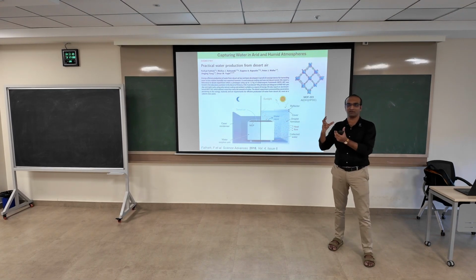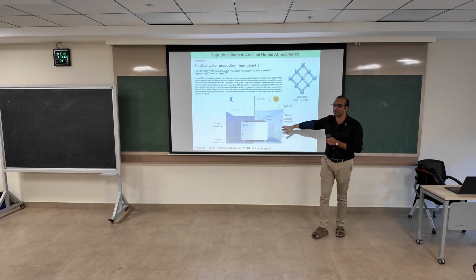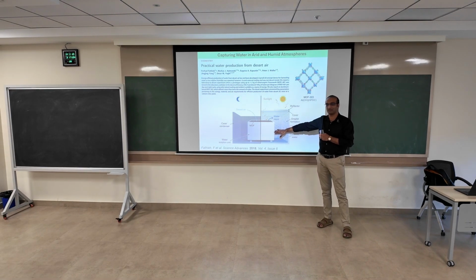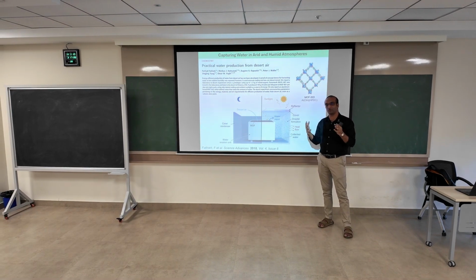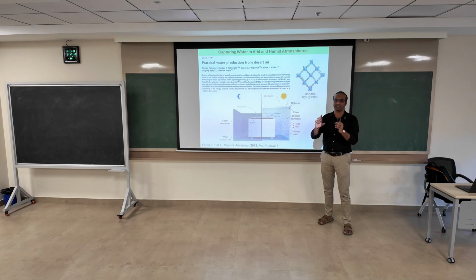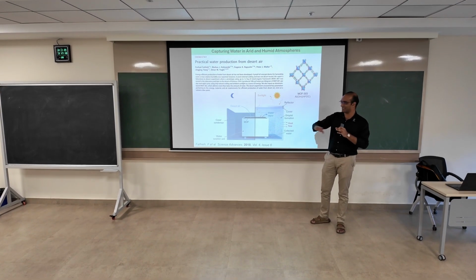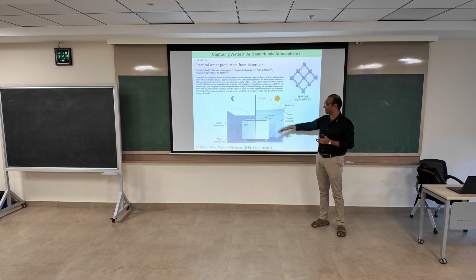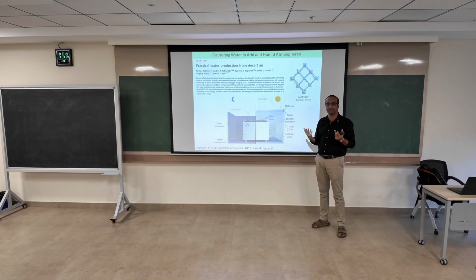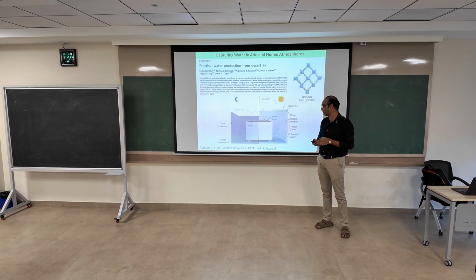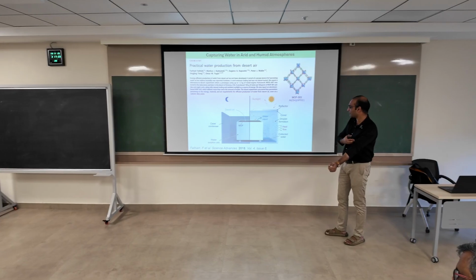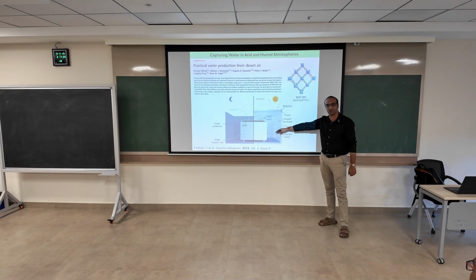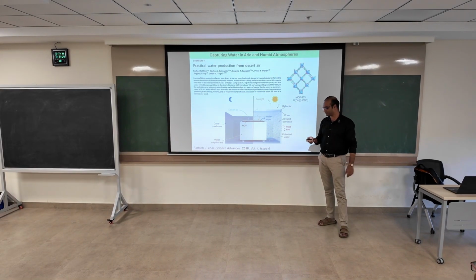They've designed a bottle. It's just that it sometimes starts to fail when you go to higher temperatures, or higher quantities, like if you want to do it on a kg scale. So it's still a concept. It's not fully developed yet. They've been able to show it for small scales. When you start industrializing a process like this, adsorption of that water introduces more heat, and that makes the material more unstable. But ultimately they've proved that you can use it to collect water from the air.